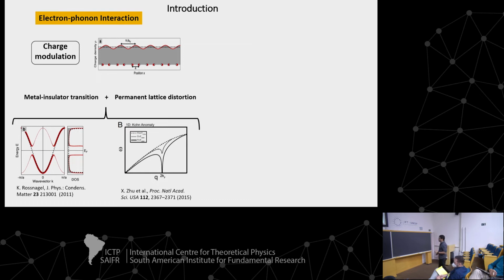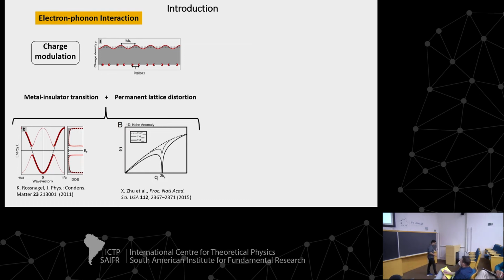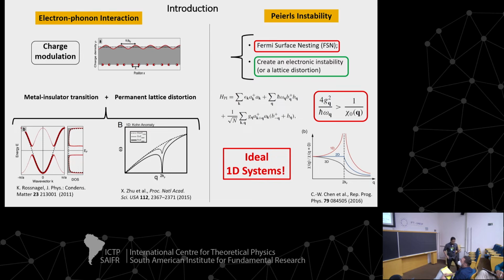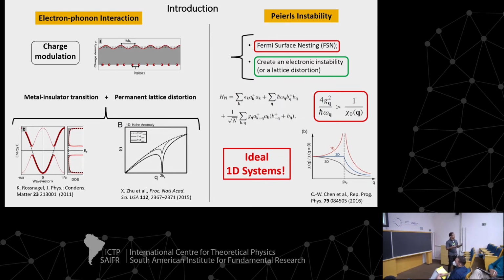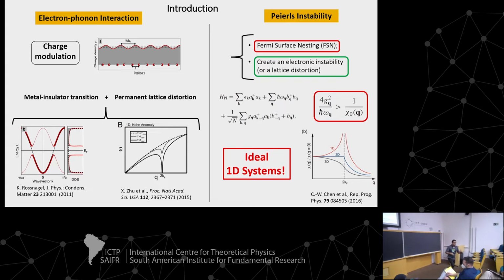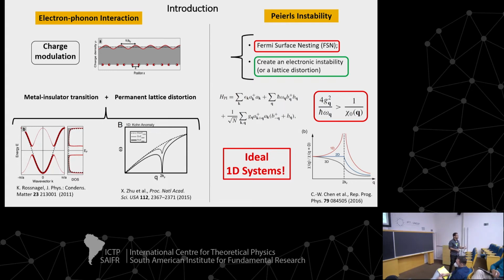This kind of phase was previously analyzed by Peierls. Peierls was the first one to give a mechanism for this kind of problem. He showed that if you have nesting in your Fermi surface, you have a divergence in your electronic susceptibility, and then any electron-phonon coupling that you put in your system leads to this charge modulation. And this happens in nature, indeed. This was my talk here four years ago about the nature of charge density wave.